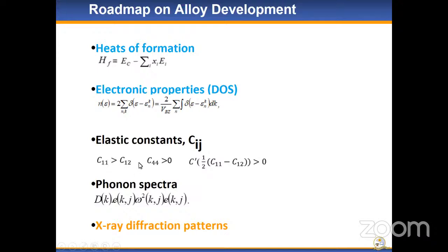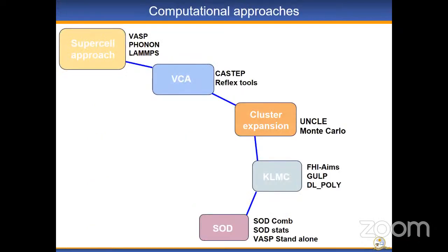I think for the elastic constants, I'm just putting some few conditions that a particular material, when it's predicted or developed, has to satisfy, where we're able to say this is more stable when certain parameters of the lattice, like C11 greater than C12 and C44 greater than 0, are positive, and also the shear modulus is positive. So there's quite a lot that one can look at, but I'm going to show a few slides on this just to show you what I'm referring to. So now, to start, I thought I should use this slide as a guide for this presentation on computational approaches.